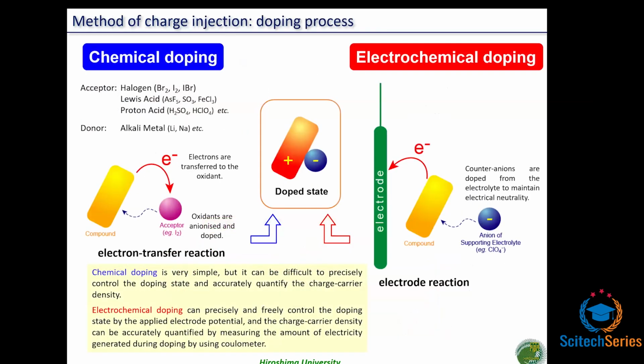In order to inject the charge carriers into these neutral polymers, there are two major types of doping techniques. One is chemical doping, which injects electric charges through a chemical reaction using an oxidizing or reducing agent. This method is very simple, but it can be difficult to precisely control the doping state and accurately quantify the charge carrier density. The other is electrochemical doping, which injects electric charges from electrodes through electrode reactions.